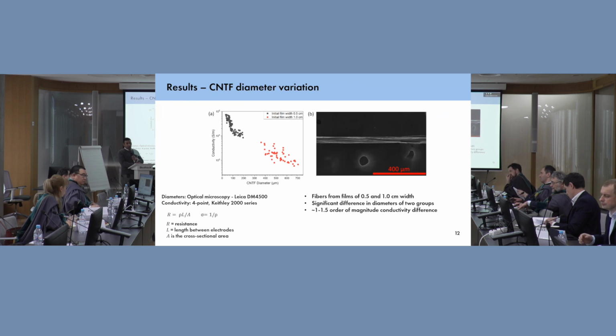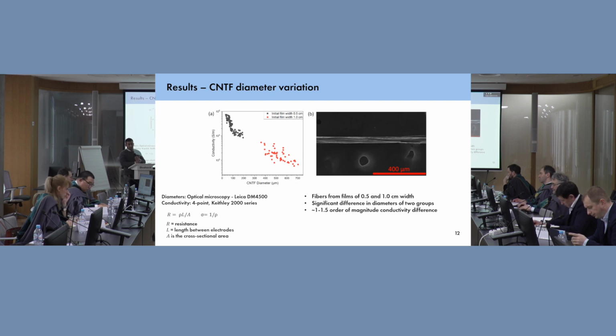So for our carbon nanotube fibers that were used, we used thin films of 2 widths to produce carbon nanotube fibers of 2 different diameter sets. One film width was 0.5 centimeters, one was 1. The thinner film produced fibers of a smaller diameter, the higher width film, a higher diameter. But the most important thing here was that we have a good difference, about 1.5 orders of magnitude difference in electrical conductivity. So we can see this effect in measurements. We have a very big difference in diameter. So if there's anything related to our physical properties, we should be able to see the difference there as well.